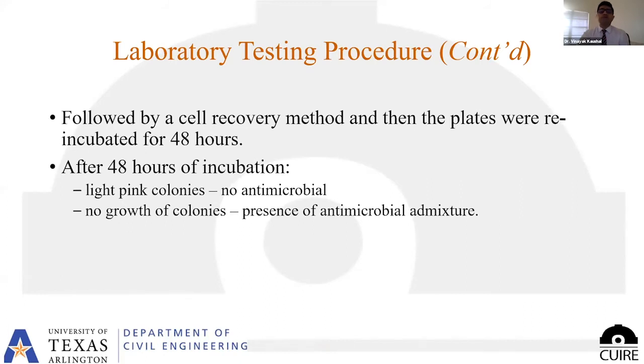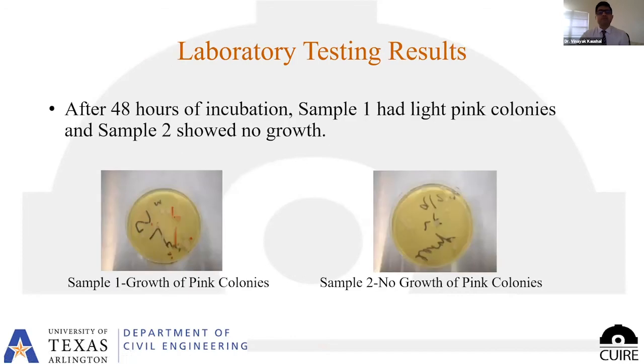Then it was made to go through a cell recovery method, and the plates were re-incubated for 48 hours. After 48 hours of incubation, it was very interesting to see that there were light pink colonies on the surface of the sample, which indicated that there were no antimicrobials added. However, in the sample in which the antimicrobial admixture was added, there was no growth of colonies. So as you can see here, sample 1 and sample 2.